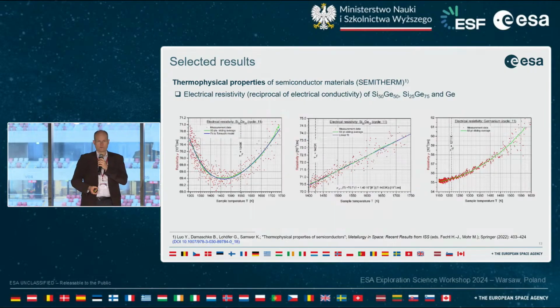The second example is from the project SemiTherm, where semiconductors have been investigated, in particular germanium and silicon-germanium alloys, looking into the electrical resistivity of these alloys. And this is shown here for different alloy compositions. So you have pure germanium on the right-hand side, and you have silicon 25, germanium 75 on the left-hand side. What you see is that resistivity in the high-temperature region, above the liquidus, again the liquidus line is the vertical line here, is decreasing with decreasing temperature. So that's quite expected behavior.